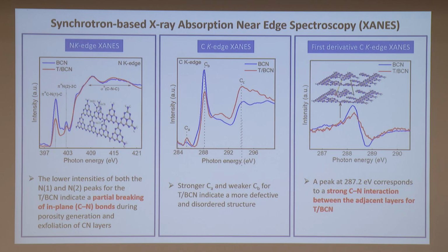So I will show you just quickly. Besides the information I just showed you, we also rely heavily on the NSRC X-ray absorption near edge spectroscopy. With this technique, we can learn exactly, once we do doping, once we make it into this form, on the basal plane we have partial breaking, and interplane, we have stronger carbon-nitrogen interaction. So all these details can be analyzed.